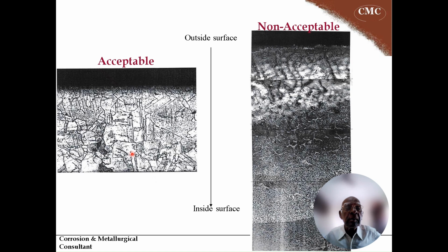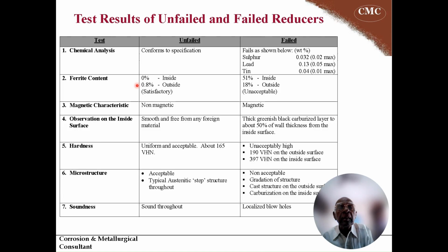So here is a comparison of the acceptable microstructure and the non-acceptable microstructure going from outside surface to the inside surface. This has not cracked, whereas this has cracked in a very premature period. And you can see the reason is the microstructure difference. Here is a comparison of the microstructural and other tests made between the unfailed and the failed reducers. The middle column is unfailed reducers, and the right column is failed reducers.